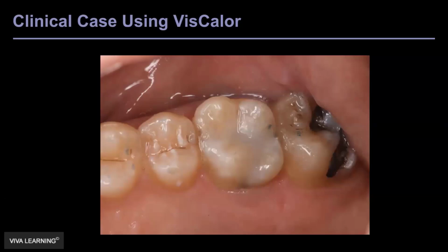Now, this was then polished with my favorite polishing system from Clinician's Choice called the ASAP polishers. But this was placed in one bulk fill technique and finished back and polished, as I said, very quickly. The composite adapts very well to the cavity surfaces and it blends in. The composite itself comes in 4 shades of bulk fill: a universal shade, a shade A1, a shade A2, and a shade A3. In this case, to counteract the graying from that composite, I did block it just a bit, and then I utilized a lighter shade.